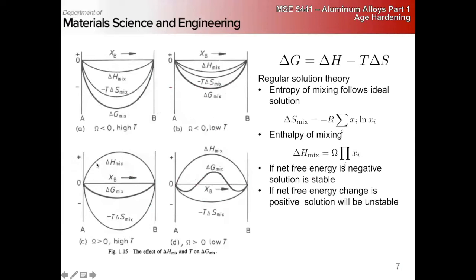We could have a positive enthalpy of mixing at a given temperature, but if the temperature is high enough, the negative component from the entropy term will dominate, and we can still have a negative delta G and still have a stable solution across the whole range.